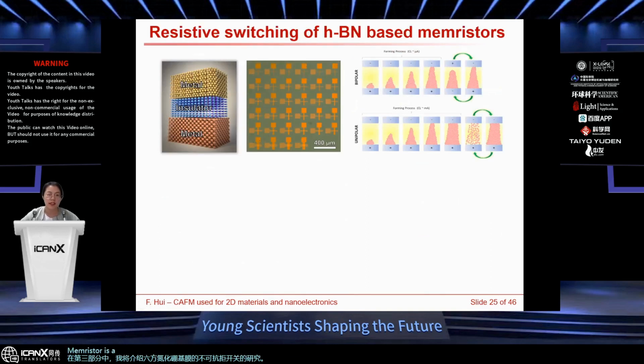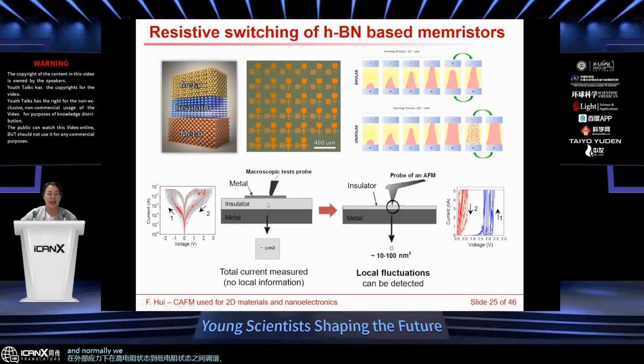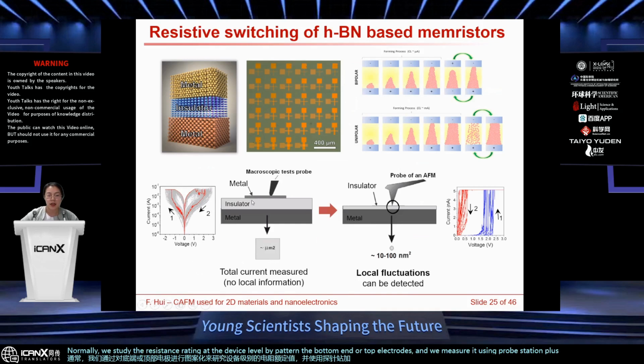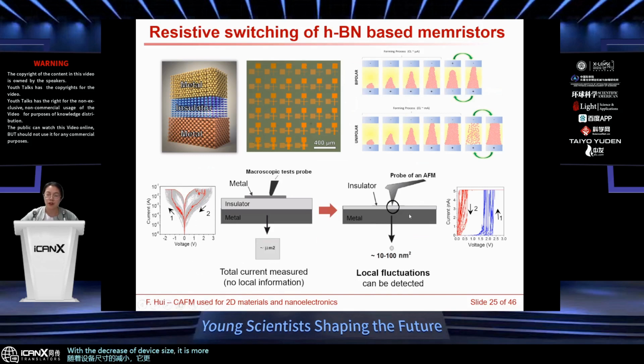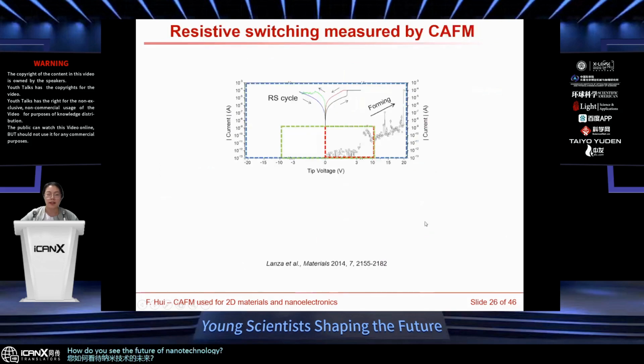A memristor is a memory device with a vertical metal-insulator-metal structure, and its resistance can be tuned between a high resistive state and a low resistive state under external stresses, for example, electrical or magnetic stresses. Normally we study resistance switching at the device level by patterning the bottom and top electrodes, and we measure it using a probe station plus a semiconductor parameter analyzer. In this case, we collect the total current under the whole electrode, and it's not easy to get local information. With the decrease of device size, it is more imperative to develop nanotechnology to detect local information at the nanoscale level.